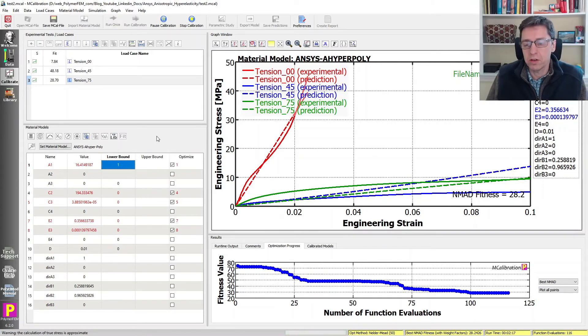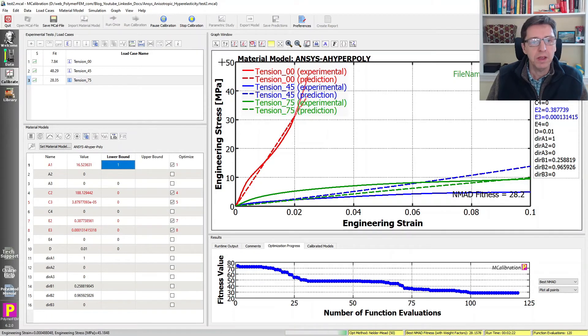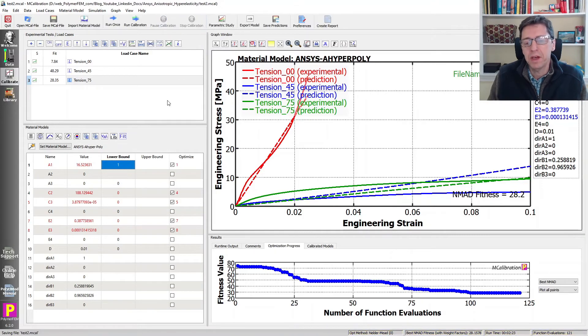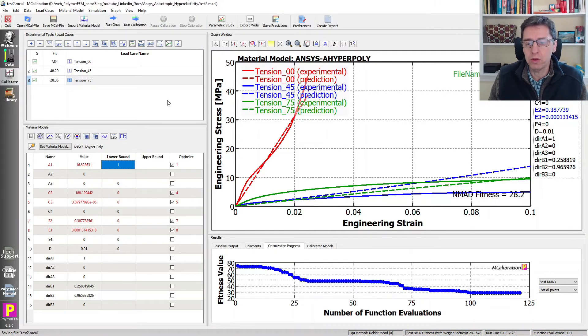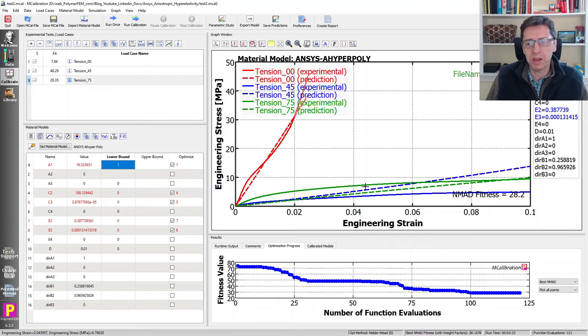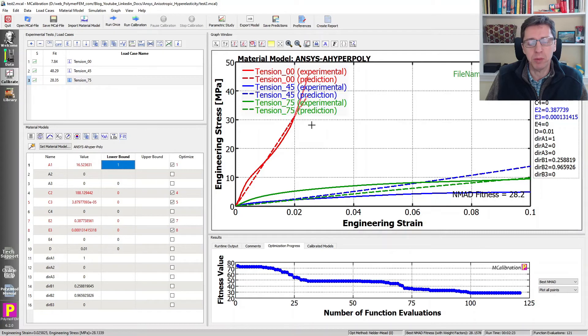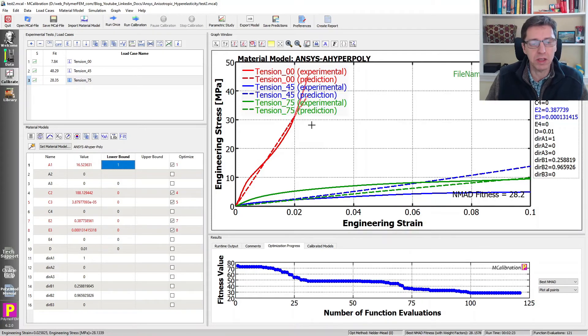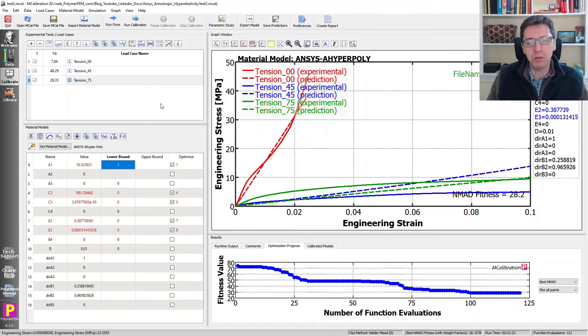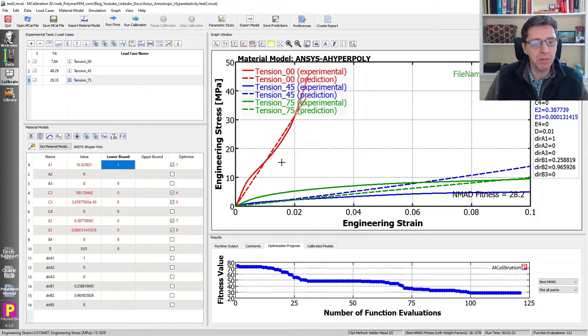This has now been optimizing for about two minutes, and I'm going to stop it. The purpose here is to demonstrate how you do this kind of calibration. If we waited longer, clearly it would get better. There are some aspects of the experimental data that are going to be difficult to capture. The experimental data rolls over a little bit, and that probably has to do with viscoplasticity of fibers, which is not part of this model. But it does a reasonable job capturing the anisotropic behavior in the different directions based on the data that we have.